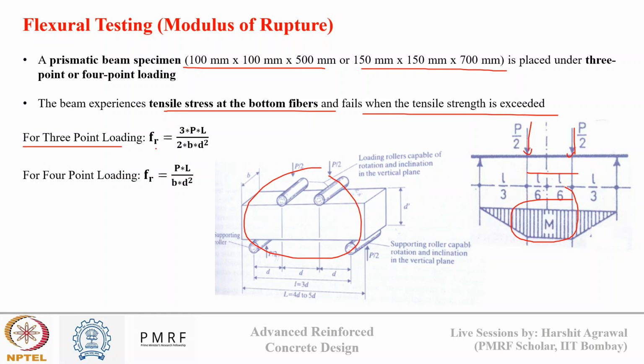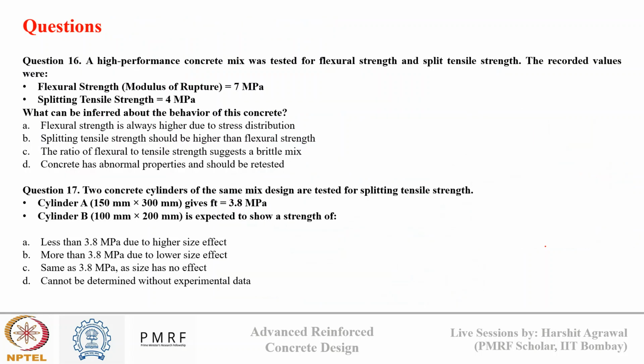Okay, so for both of these there are different formulas that have been derived. For 3 point loading, we use 3PL upon 2BD square. So this L is the length of the beam, B and D are the cross sectional dimensions of the beam. And for four point loading we have PL upon BD square. Okay, and why are these formulas different? Because of the difference in the bending moment profile in both the cases. So generally the failure happens at the weakest link where the bending moment is maximum, that is in the middle part. So from the middle the failure will happen, and that will be due to flexure failure, and that is used to determine the tensile strength of concrete, because direct tension determination is difficult.